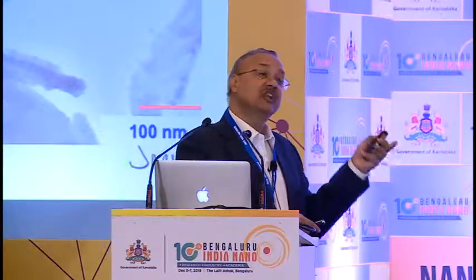Then came the question how to scale up something which is a nanotube, which people make in micrograms or milligrams. How can you create 30, 40, 50 grams, 100 grams of material in a lab? And we have done that. And these are the materials, these are the rods of polypyrroles. We call them nanotubes of polypyrroles. And these are hollow nanotubes of polypyrroles. So we added them into a fiber. So we created a fiber which has two structures, a core and a sheath. Core had nanotubes of polypyrrole, and the sheath was a normal nylon.